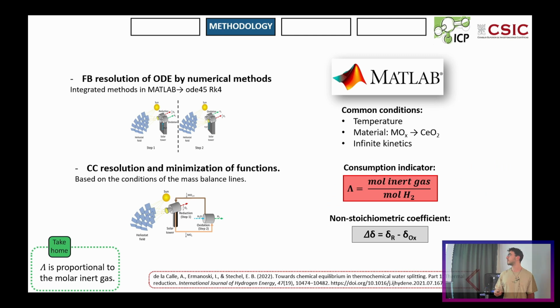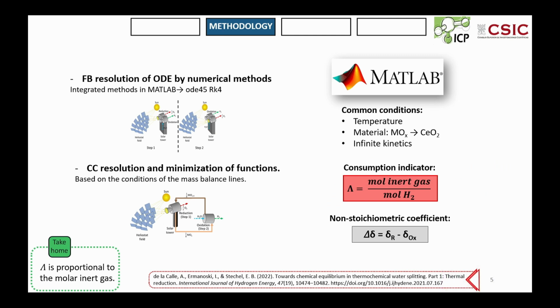How did we resolve our reactors? We made some simulations using MATLAB, and for the fixed bed system, we resolved them by iterative numerical methods, which were native in the software. And for the countercurrent system, we assumed chemical equilibrium along all the flow path. We take into account some common conditions like the temperature, the material, and the kinetics. And also, it's important to remark that we used the lambda term to track the consumption and the non-stoichiometric coefficient to track the reaction process.